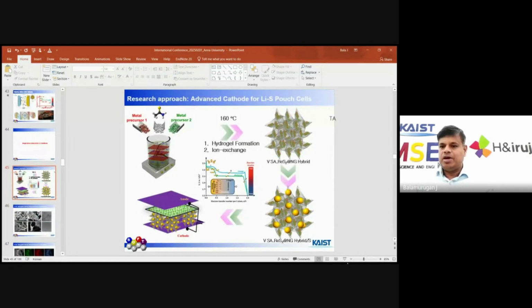We fabricate the lithium sulfur battery by making the vanadium single atom with the rhenium sulfide anchored nitrogen doped graphene networks. You can see this is the strategy for the synthesis methodology. We fabricate the material by placing vanadium single atoms into the rhenium sulfide networks, and they may be homogeneously distributed over the graphitic carbon networks.